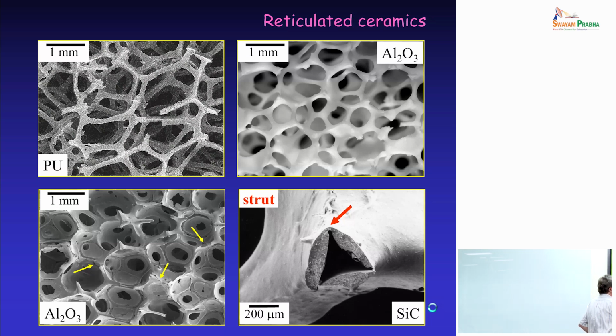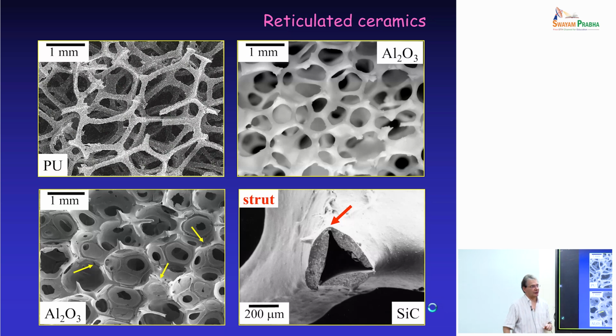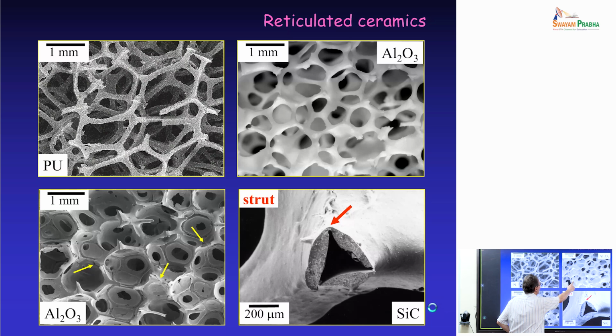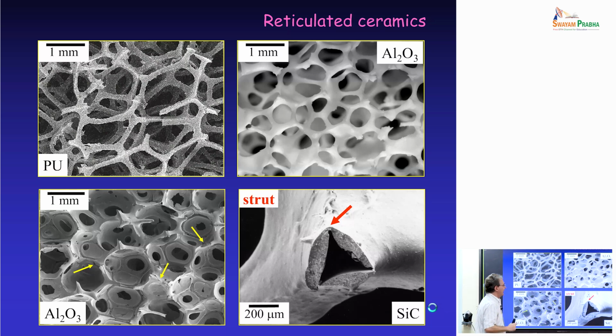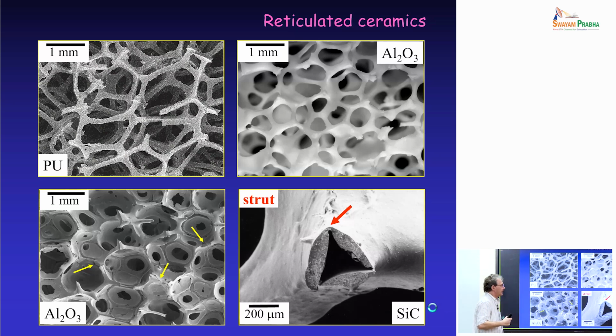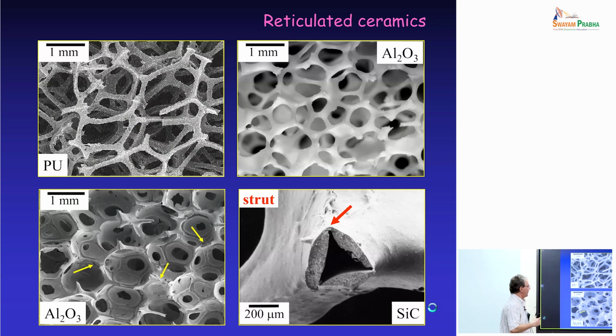So you can see the polymeric foam, and in order to have such a nice open structure, what people do is that they make the foam and then they use a hydrogen-containing mixture that explodes and breaks all the cell windows, and you obtain a very nice interconnected porosity. After dipping and carrying out properly the process, you obtain the replica. That's why this process is called a replica. The term for the material is reticulated ceramic. And if you don't expel completely the slurry, after sintering, you have certain amounts of cell walls, but you can still retain the permeability. So here, of course, the permeability is lower than there.